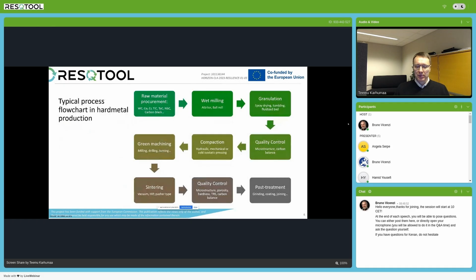And as you know, the hard metal tools and parts are produced via powder metallurgical methods. So raw materials are in this case all in powder form, tungsten carbide and cobalt, but then also other carbides or even other binder phases can be used. The materials are mixed and milled typically in an attritor or ball mill. The powders are granulated so that they are free-flowing powders, and after that there is typically a quality control step where microstructure, carbon balance, flowability, etc.